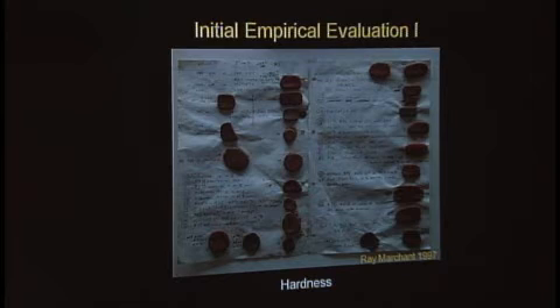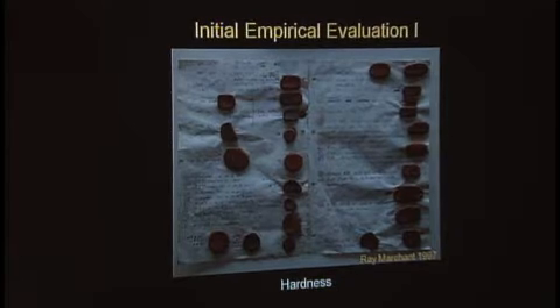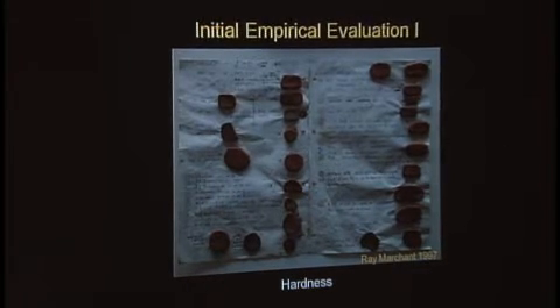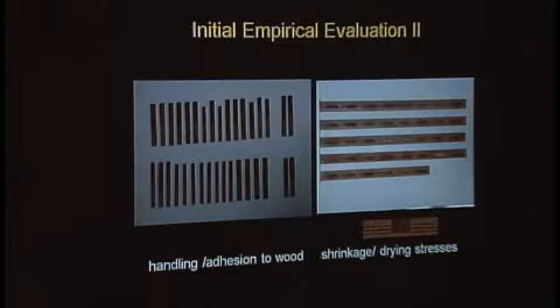These are Ray's early studies in 1997 when he started to look at the alternatives, what was around commercially for gap filling materials. A lot of these are conservation grade materials, but as he found, and I found subsequently, very unsuitable as gap filling materials. These are his first empirical tests looking at the hardness by simple fingernail testing and thumbprints, and then adhesion to the wood, simply by applying them onto wood sticks and seeing how well they stuck.